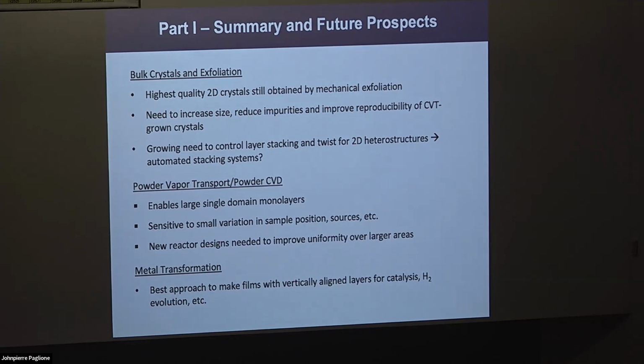So typically you grow in an excess, usually people want to grow in excess chalcogen, largely because it depletes through the process, and a lot of it gets wasted downstream. So that's one reason. And usually you want to have a low transition metal. Ultimately, you want to grow monolayers at a time, right? And so you want to be able to really control the nucleation density. And so if you just weigh them in the sense like 2 to 1, it doesn't actually grow high quality crystals. So you actually want very high chalcogen to transition metal ratios in the thousands. Okay, so that's usually how you think about it, largely because of this vapor pressure issue.